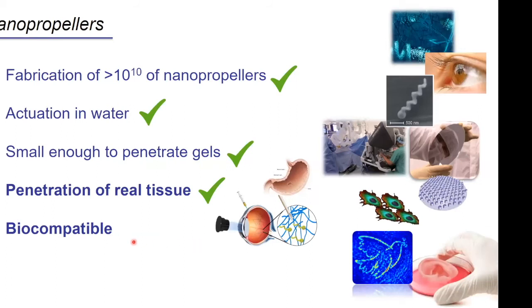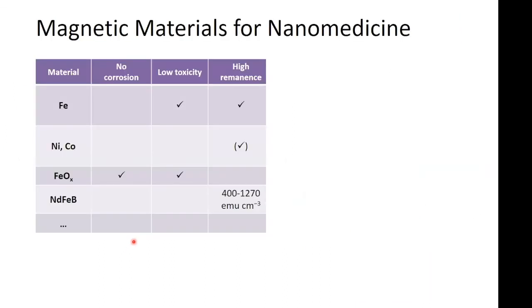And now, as a very last comment about biocompatibility, because we're using inorganic materials and we're using magnetic materials, that sounds like it's not something you would want in your body. But there's good news on this front. And the good news is really a remarkable material that we've started to work with. So you're familiar with nickel, cobalt, iron oxide. Bottom line, to cut a long story short, if it has good magnetic properties, it's toxic. If it's compatible, it usually has weak magnetic properties. We want strong magnetic properties so we can operate with weak fields and transmit through tissues.